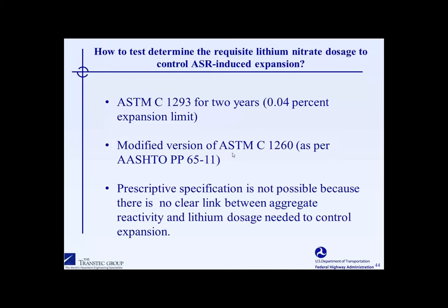You cannot use the standard ASTM C1260 as it exists to evaluate lithium. And again, it has to do with the fact that you have an infinite amount of alkalis outside of the prisms or the mortar bars. And on the inside, you would have a finite amount of lithium that was put in the bar initially, but that amount of lithium will be completely overwhelmed by the external alkalis. So we do have a modification that we have recommended where one can modify the ASTM C1260 test, and then you could potentially use that to evaluate lithium admixtures and get results in 2 weeks.